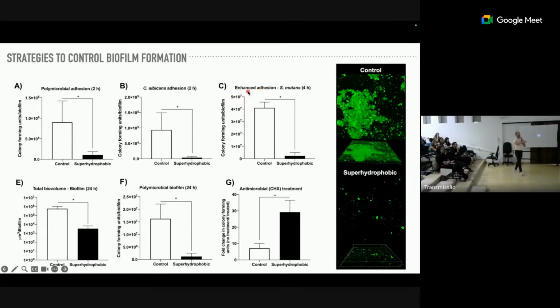We also checked for Streptococcus mutans. There's no relation with peri-implantitis, but Streptococcus mutans by itself is a very sticky biofilm because they have a very strong extracellular polysaccharide matrix. Using this sticky biofilm, we also observed a lower content of Streptococcus mutans in the superhydrophobic. We also checked the biofilm at 24 hours, and we observe lower levels in the superhydrophobic.